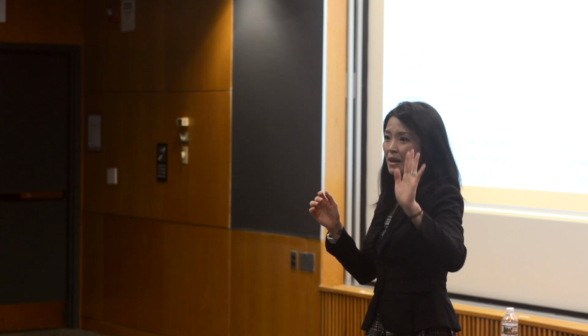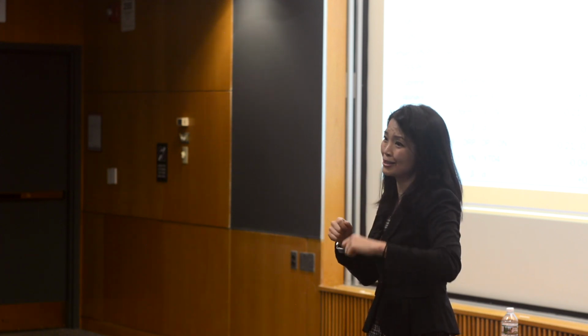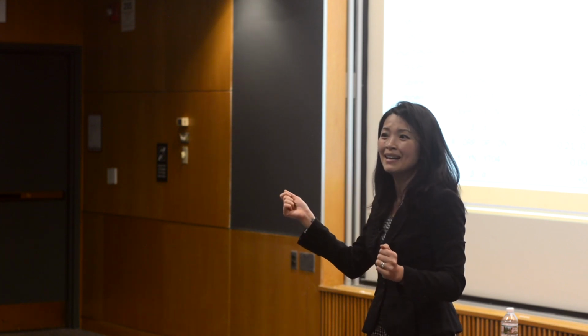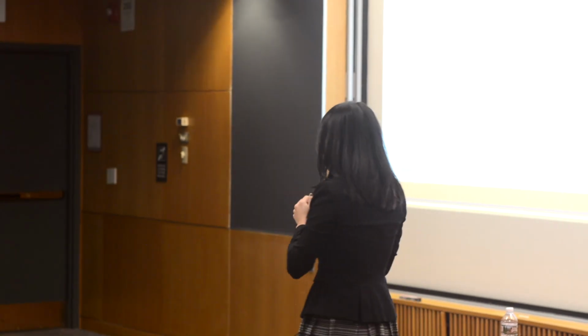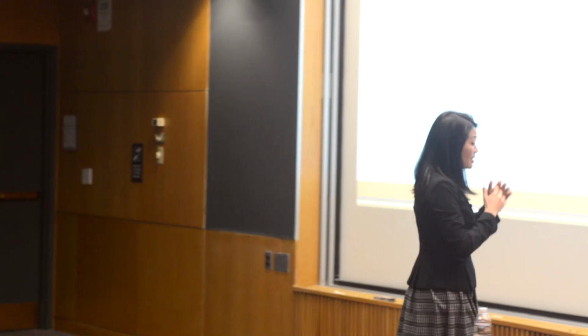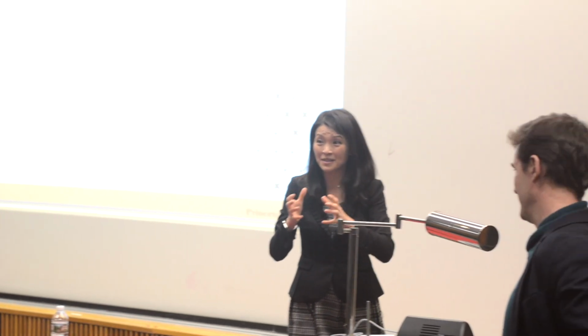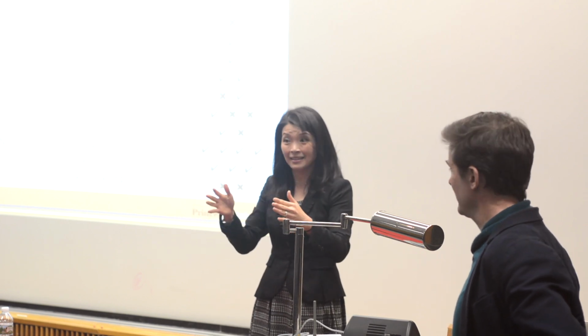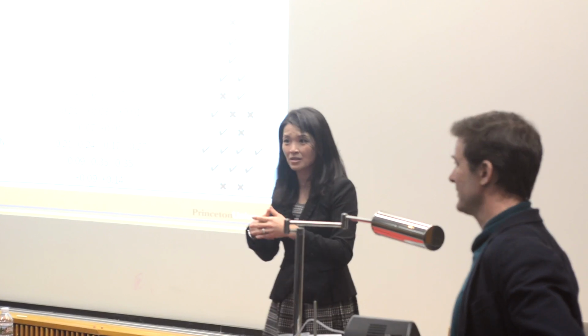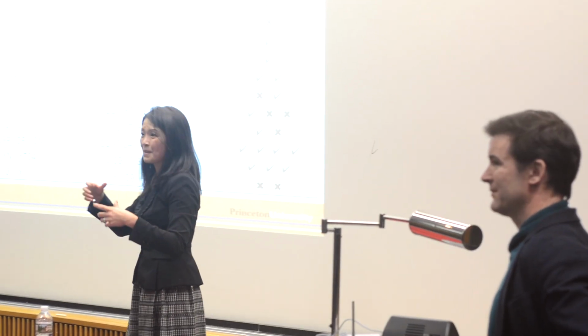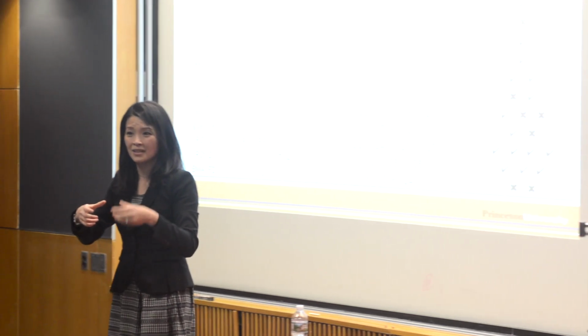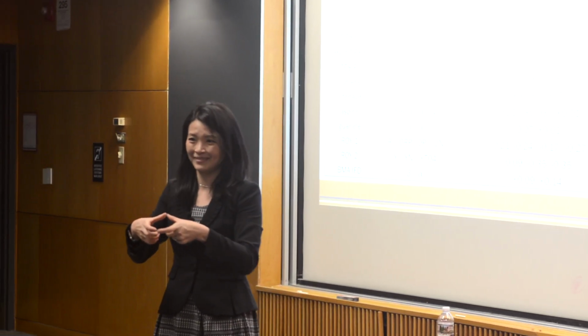I can guarantee you grain boundaries play a role. Now I can argue that it slows things down or it hastens things up. I can have arguments both ways. We haven't done the experiment. The one single data point we have is if you do a transformation with single crystal, it happens much, much slower. But that's one specific example. I can see grain boundaries facilitating this transformation because they can nucleate it. I can also see it the other way around, where grain boundaries retard this transformation because once you nucleate, you can only go so far.